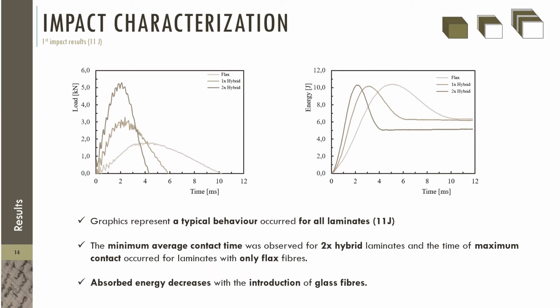The results indicate that load and energy versus time present a typical behavior for all laminates. We can see here in the load versus time graphic that the minimum average time was observed for the 2x hybrid composite, and the maximum contact time occurred for the composite with only flax fiber. We can also see that the absorbed energy decreases with the introduction of the glass fiber.